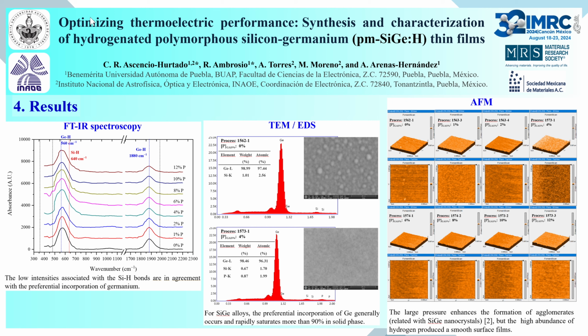The figure at your right shows the AFM 3D surface images of polymorphous silicon-germanium thin films and depicts the evolution of surface topography of the samples as the gas phase phosphorus content was increased from 0% up to 12%. The mean roughness for doped films reaches its maximum value of 0.6 nanometers at 4% phosphorus content and decreases if the phosphorus content increases or decreases from this point.